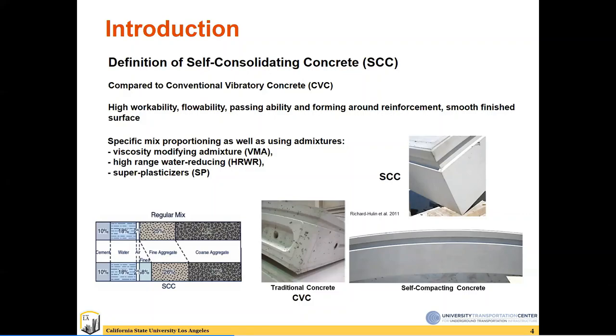These admixtures could include the viscosity modifying admixture, or VMA, or a high range water reducer, which lets you reduce your water to cement ratio, and you know that decreasing the water to cement ratio could give you a higher compressive strength and higher performance of the final product. And also superplasticizer, which can really increase the workability and flowability of the SCC mix. Again, as you can see in the bottom right photo, the finished surface of the SCC is very smooth compared to conventional concrete, specifically in this case for precast tunnel segments.